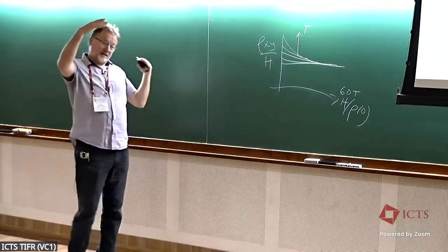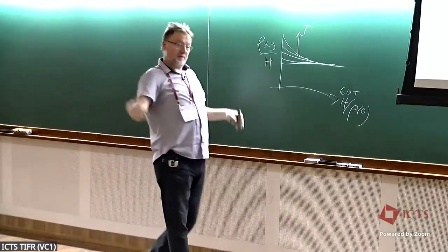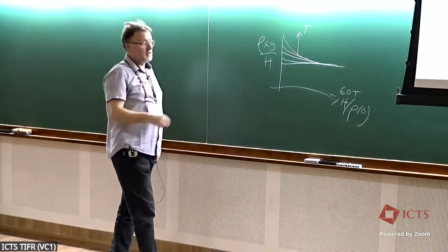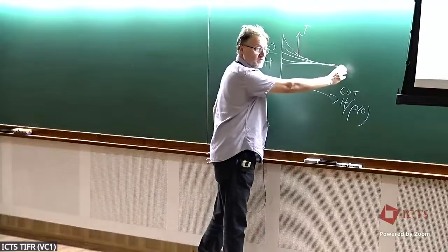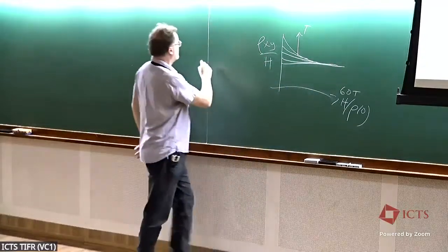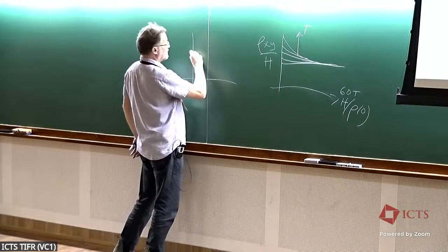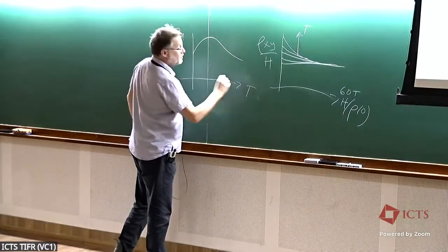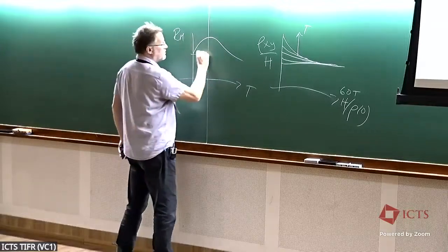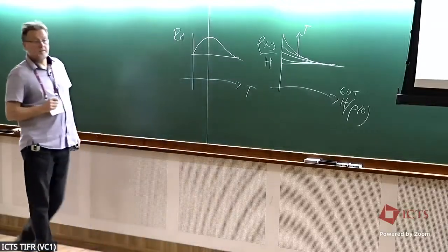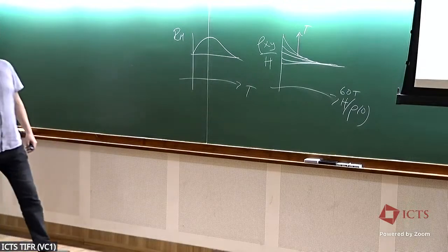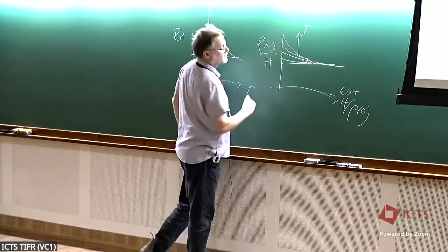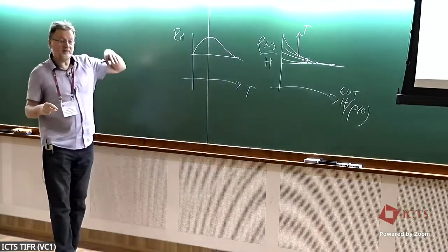What's interesting is that the Hall coefficient temperature dependence you can explain with some anisotropy, which is washed out with field. So if you were plotting your high field Hall coefficient, here's your zero field Hall coefficient, RH. If you were going to infinite field, it would be like this. Of course, we never get that far, and this is cut off by our field range, but it appears to be approaching asymptotically the same value.